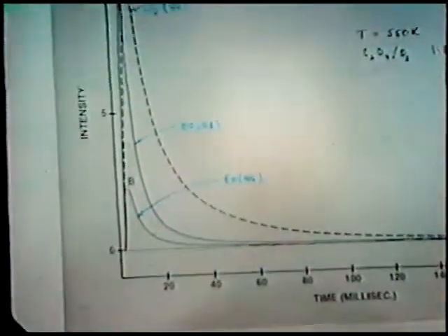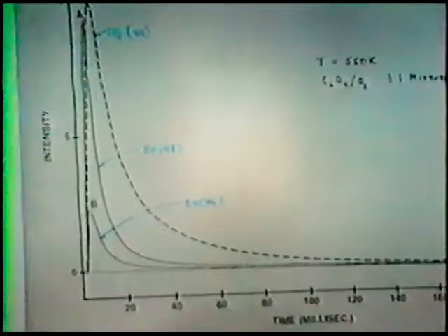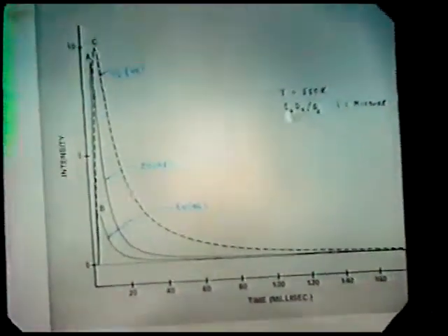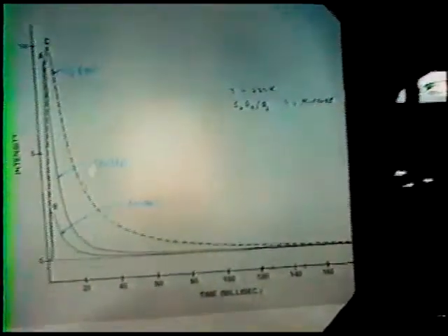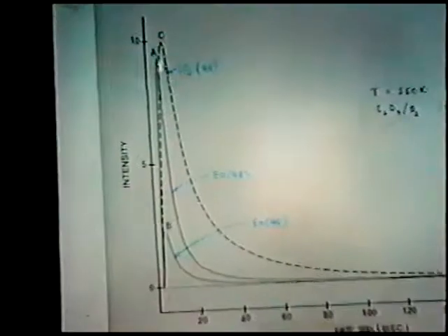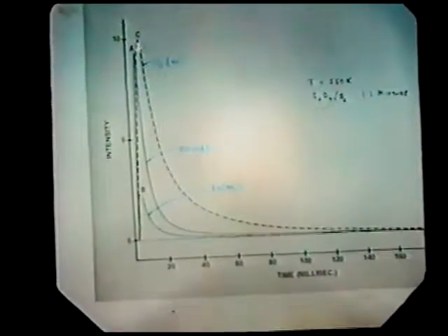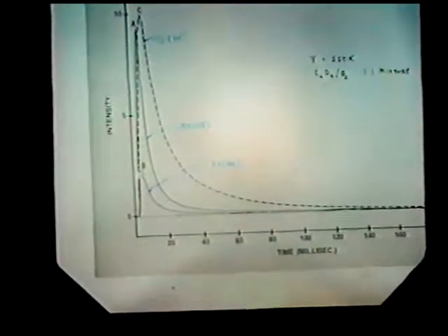This spectrum, this transient evolution of products, is characteristic of a pulse in which both ethylene and oxygen are pulsed together in a 1-to-1 mixture. The temperature of the silver was held at 550 Kelvin. And here you see the evolution of ethylene oxide, as shown by both mass 48 and mass 46, curves A and B, and of CO2, mass 44. And you can see at a glance that the characteristic time for the evolution of the CO2 is longer than that for ethylene oxide. And by looking at the cracking fractions for ethylene oxide, here I show two of them, we could convince ourselves that in fact it's ethylene oxide and not the acetaldehyde.